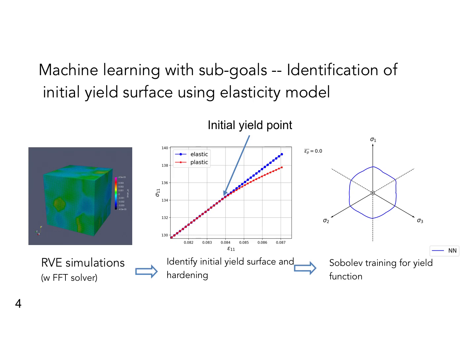A material doesn't really have fixed plasticity. Instead, the plasticity model may actually have a yield surface that is evolving. What that means is that if I have a plasticity model that initially has a yield surface that looks like this, as I accumulate more dislocations or other plasticity behavior, the yield surface may change into another shape.